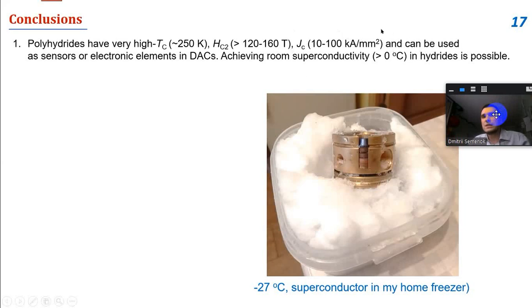And they also have very high critical current density. So it's very interesting because it means that they can be used to conduct electricity with extremely high density, higher than all known materials. And they can be used also as sensors or electronic elements even now in diamond anvil cells, because there are optical windows and we can send some useful signal and detect the electrical response using the electrical leads deposited on diamond anvils. So now almost everyone can have their own superconductors. In my home freezer, I have such a diamond anvil cell which has a superconductor which goes to the superconducting state at about -27 Celsius.